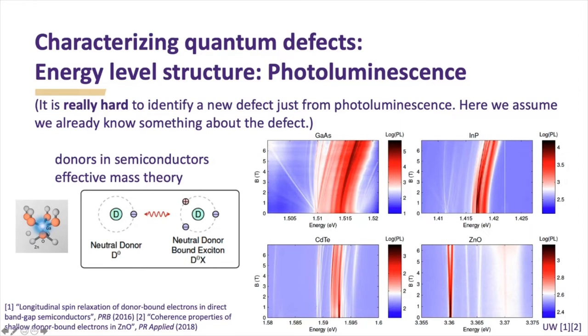And so here I'm showing four different semiconductors, gallium arsenide, indium phosphide, cadmium telluride, and zinc oxide, where we plotted the intensity in a color map of the photoluminescence, and it's a log scale, so you can see some of the fine structure, as a function of magnetic field. And as you do this, what you can see is that the energy levels can shift and split, and these individual lines here are those transitions that we're going to use for the qubit states. It's very obvious in zinc oxide, where you see just two levels in this particular case. And so we can use what we know about effective mass theory, and we can understand these splittings, and then we can identify those energy levels that we want to use as qubit states and as optical states.